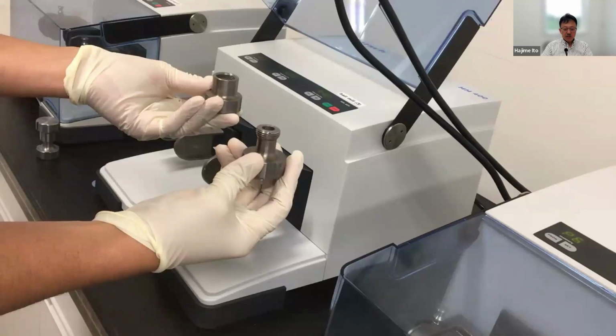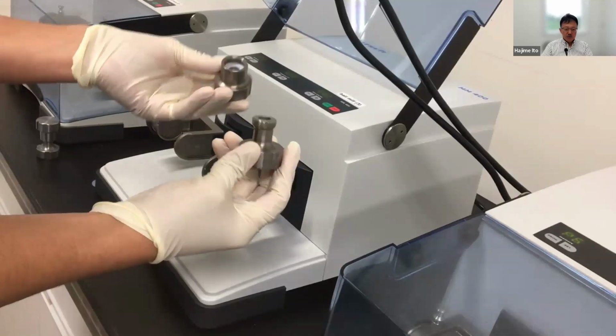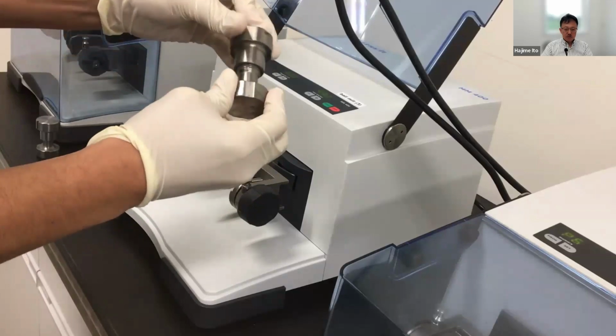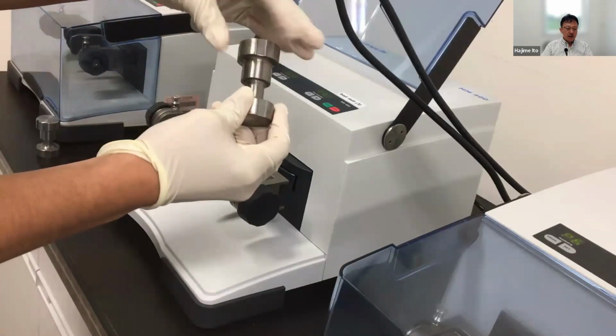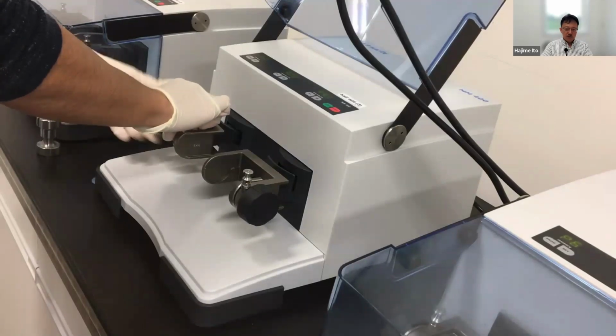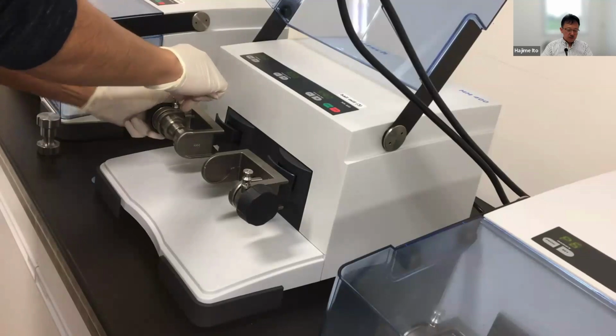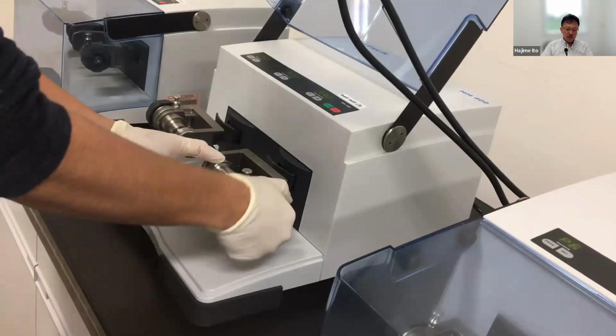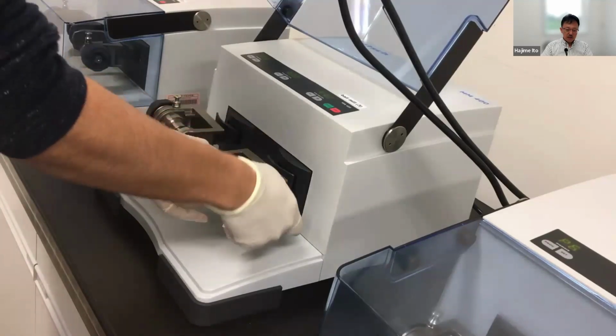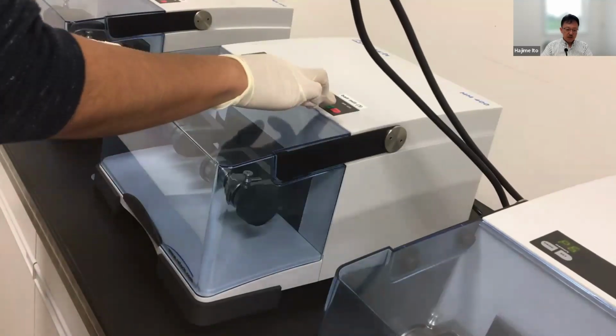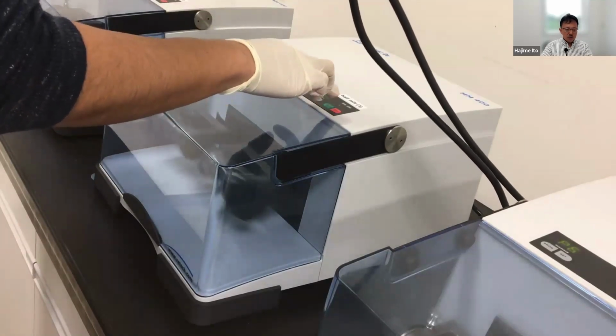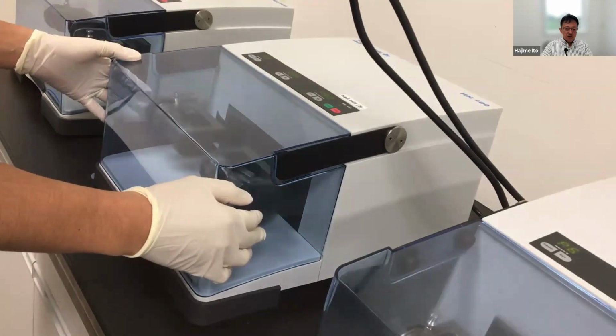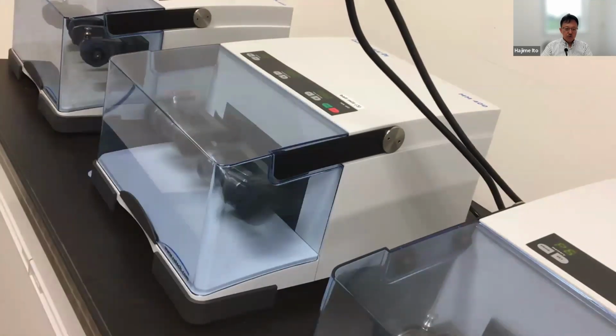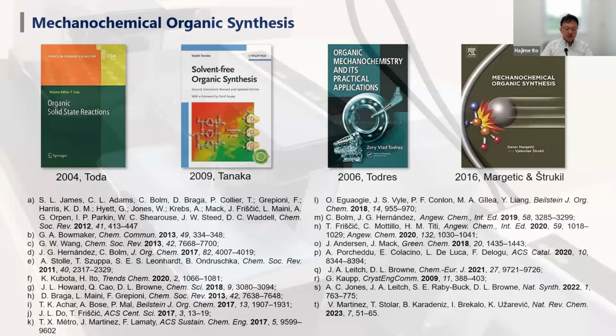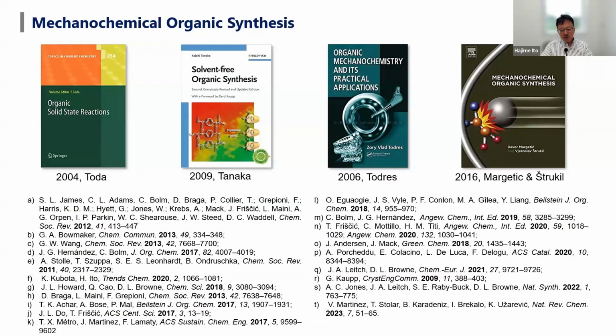This is a ball milling machine. We put some balls and substrates into the jar, and we put that jar into this organic ball milling machine. We close the cover of this machine, and the reaction can be started by just pushing the start button. The vibration of this machine is typically 30 Hz, not super high, but this is enough for promoting organic reactions.